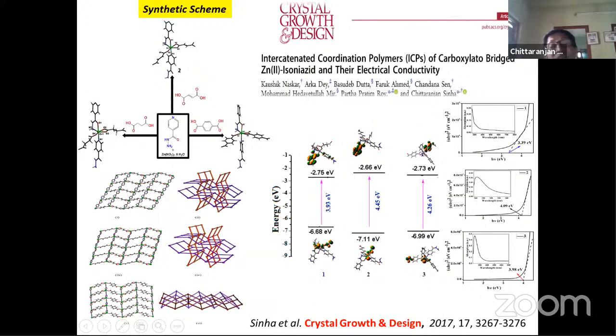But you can see the resistance is also decreased from 540.96 ohm in the dark phase to 421.22 ohm in the light phase for the activated molecule, while the iodine absorbed activated molecule, its dark phase resistance is 451, and the light phase is much reduced to 262.83. That means the molecules on iodine adsorption enhance their conductivity and reduce the barrier height. And this has instigated us to design many other molecules using many connectors.